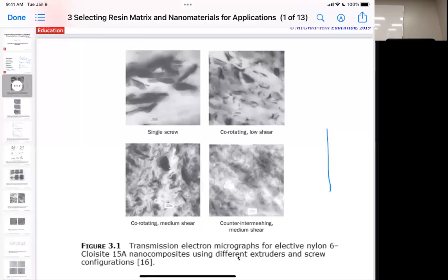That's why in almost all of these you see a whole bunch of nylon 6. Nylon 6 is dirt cheap, and it has great surface energy. It's got a lot of hydrogen bonding. So it has great energy that goes onto the surface of your metal oxides, your clay platelets with surface defects, because there is a certain negative charge on the surface, and so it binds to those really well. And we end up getting very good compatibilization on a chemical, atomic level.